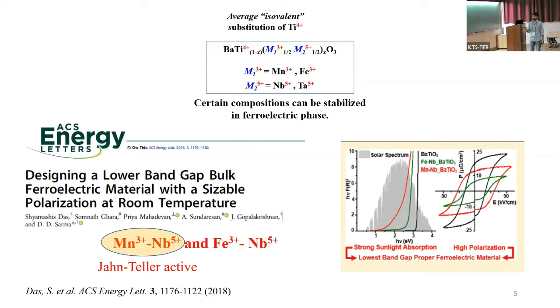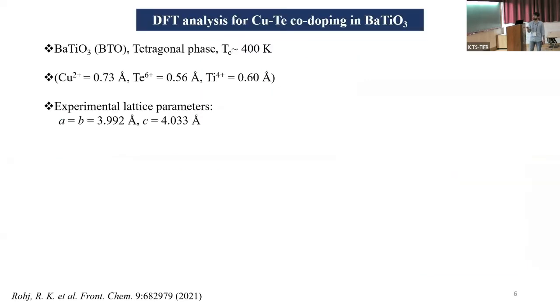Carrying forward this work, what we did was choose copper and tellurium as our co-dopants and carry out density functional theory analysis for this dopant pair in barium titanate. We chose copper and tellurium because copper 2+ has a size of 0.73 angstrom. Tellurium 6+ comes with a size of 0.56 angstrom, which is near the average size of titanium 4+, that is 0.60.